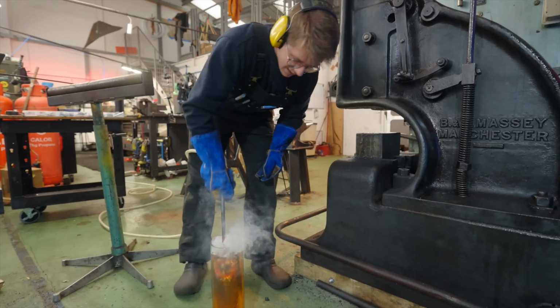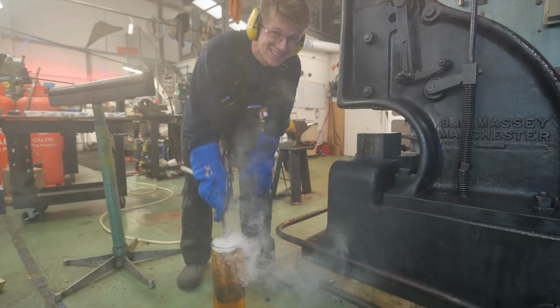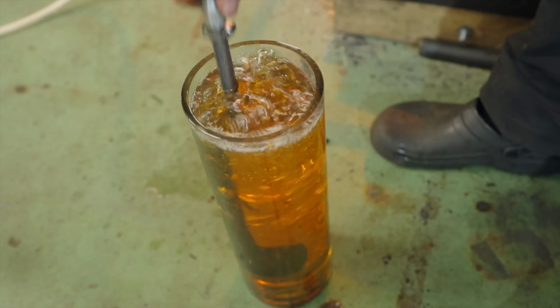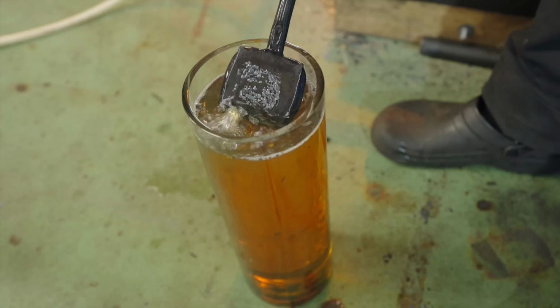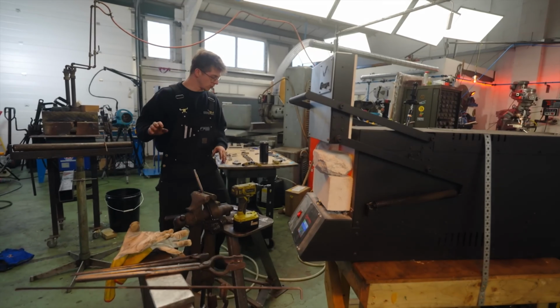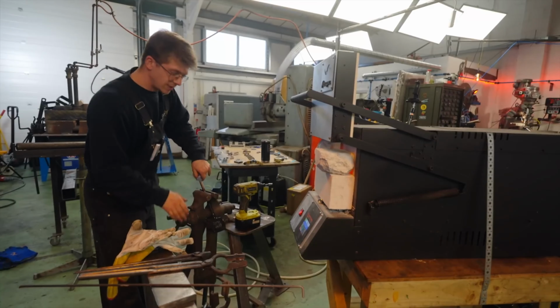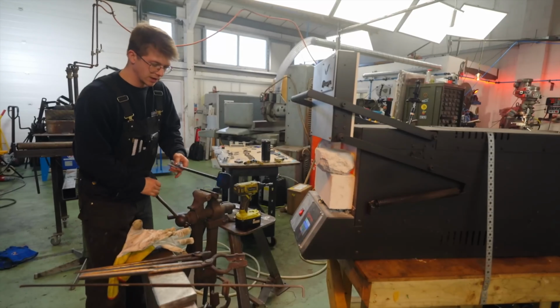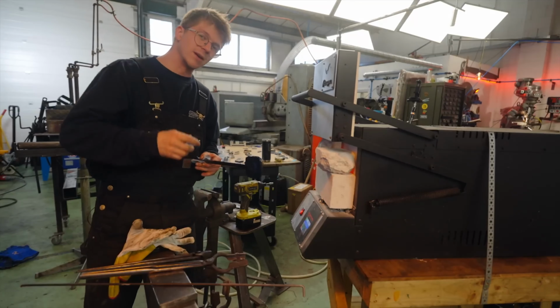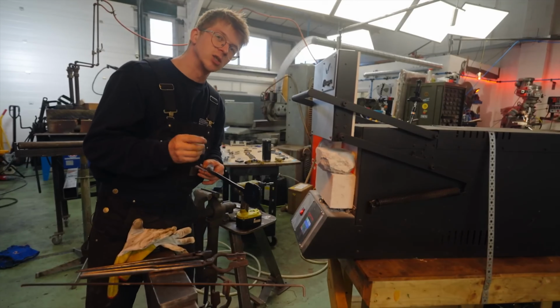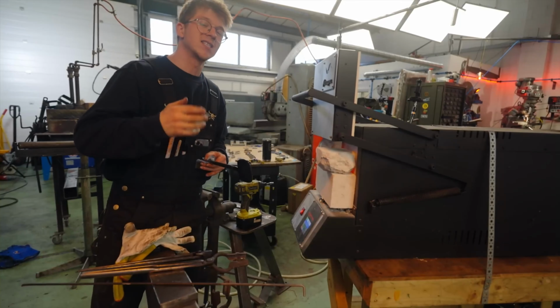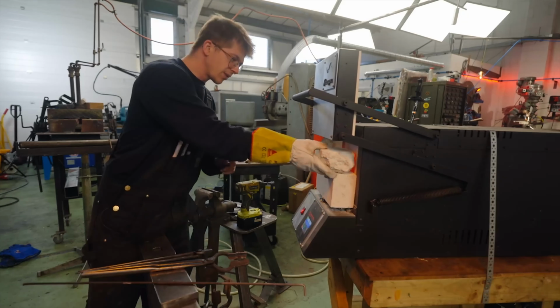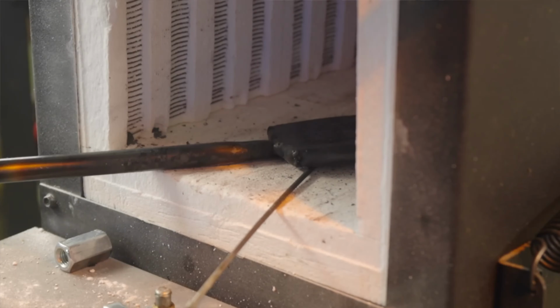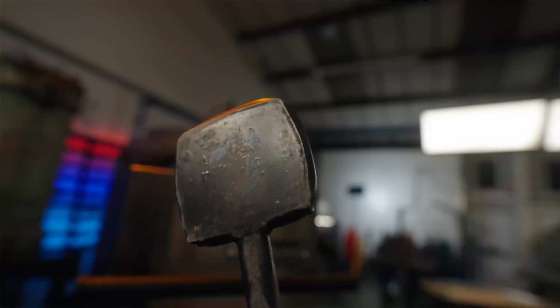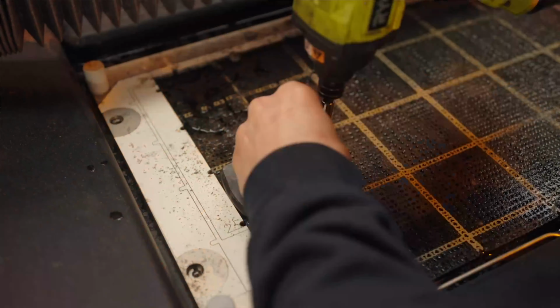Quench. That's wild to do. There's the argon bubbling out. That's so cool. All right, we're gonna need to run a slightly different order of operations because obviously I'm not gonna be able to cut the hardened steel and process it to size. And also, if you leave steel hardened but not tempered for too long, the steel itself can break. So we're gonna dump the heat out of the kiln, temper it as soon as possible. And this is then going to be the perfect time to use the Waterjet again because it will be impossible to bandsaw the hardened steel.